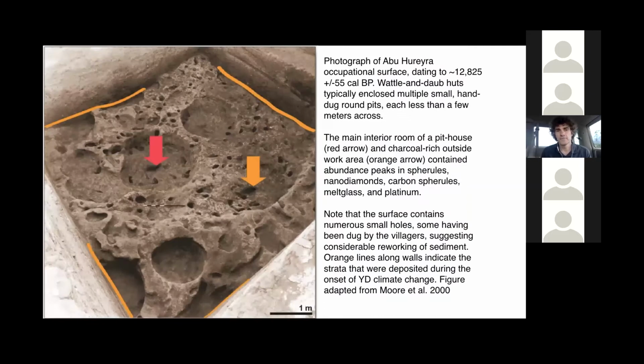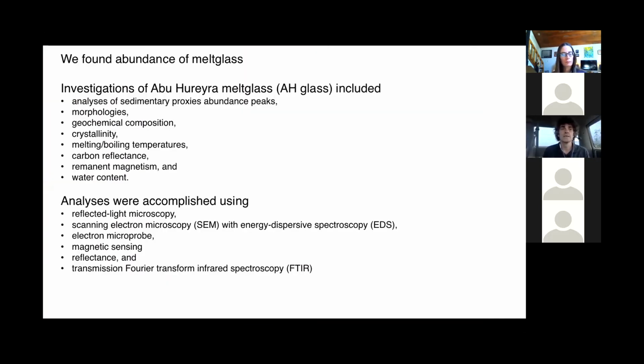Now here's the pit from which most of the samples you will see come. With the red arrow is a dwelling where people lived. The orange-yellow was the working area. There's 1 meter for scale down there, and a lot of these holes are different things that people were digging in order to utilize the surface at the time of living there. Also notice this orange line, which is the level that has all these weird features, and I will be talking about it. There's the occurrence of nanodiamonds, the occurrence of microspherules, and there is a lot of melt glass, about 30% in that layer. This is what our analyses were done on.